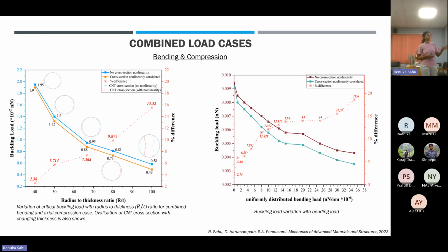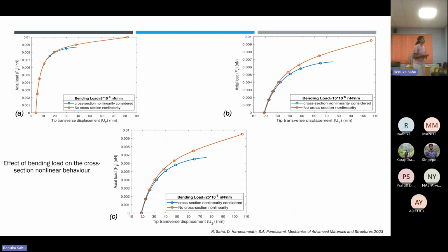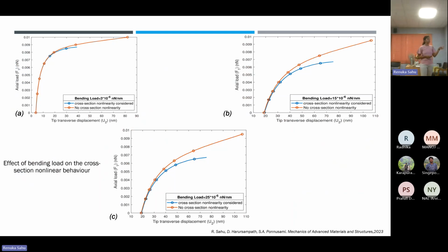We also studied how the buckling load varies with the applied bending load. Bending load has a larger contribution to the difference between the cross-section ovalization model and the linear cross-section model. We compared the different bending loads for the two cases, with and without cross-section nonlinearity, and this shows that bending load has a higher impact.